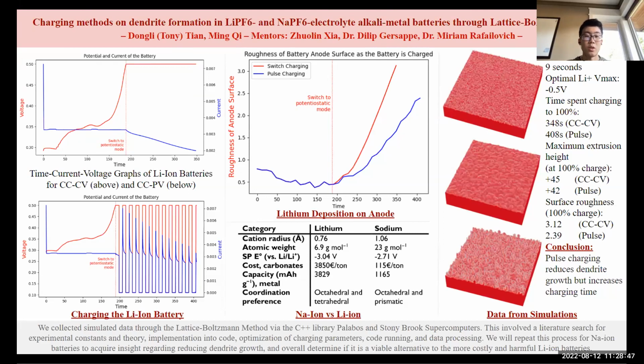As seen in the images to the right, charging the battery led to visible growth of dendrite structures. However, pulse charging at a frequency of 9 seconds increased charge time from 348 to 408 seconds, yet lowered the RMS size of dendrites from 3.1 to 2.4 micrometers and reduced their maximum heights from 45 to 42 micrometers. This shows that pulse charging, while taking longer, does lead to reduced dendrite growth, vastly improving the safety and lifespans